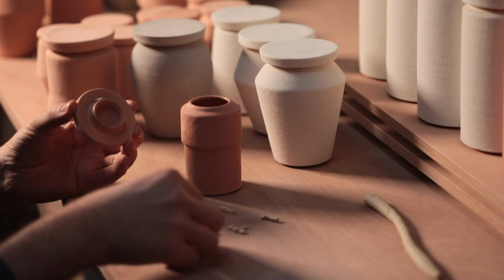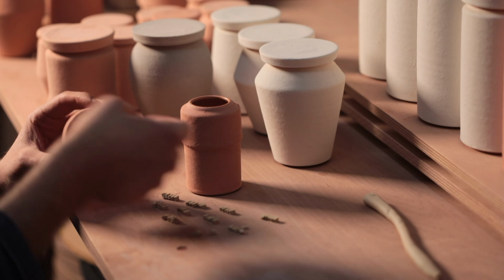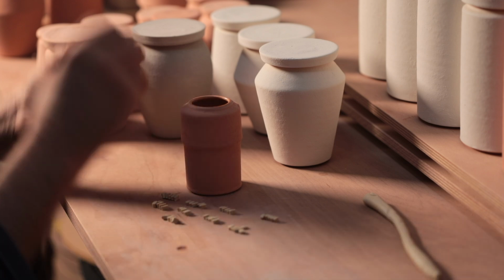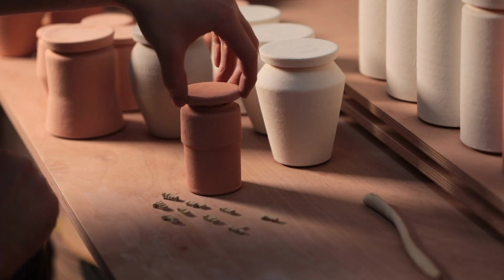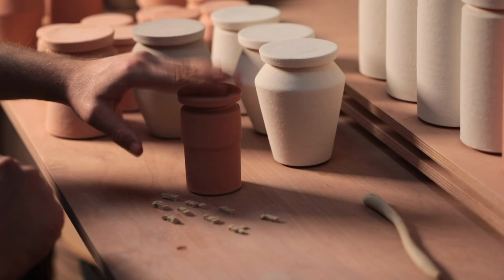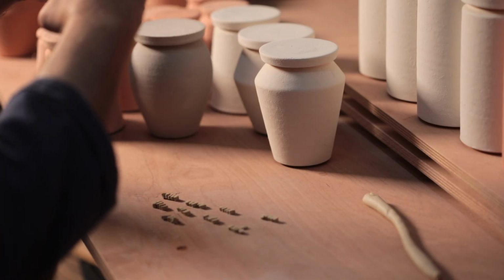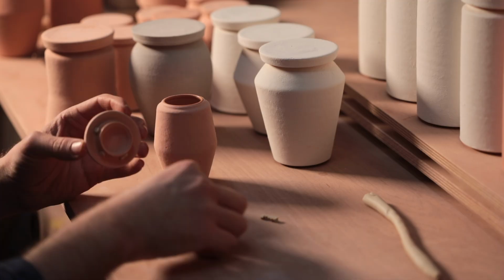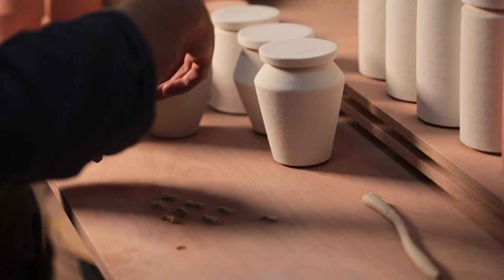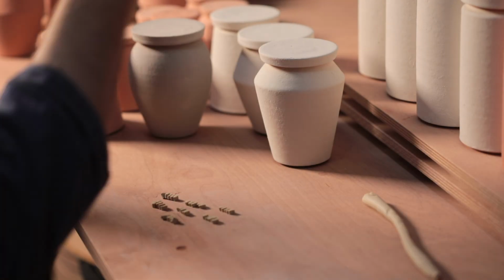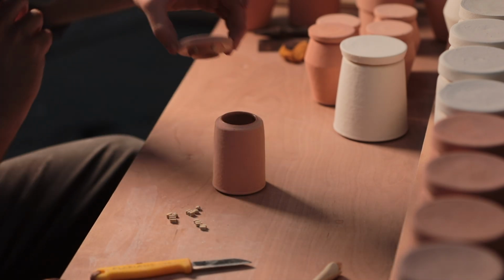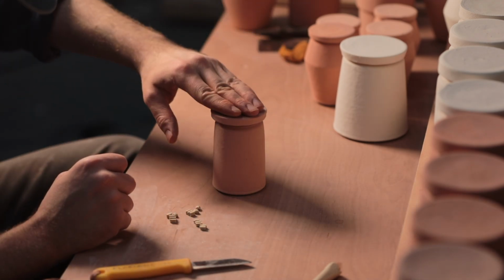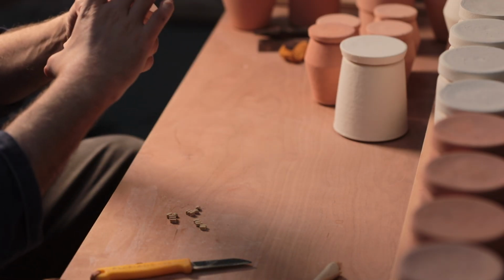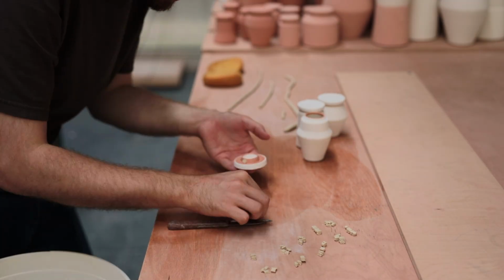I roll out long coils of the wadding and then cut them into much smaller bits, and then I press 5 of these beads of wadding onto the wax on the underside of the lid and then press it into place on the body of the jar, making sure that the clay of the lid doesn't come into contact with the rim of the jar, as at this higher temperature, if clay touches clay, there's a chance it can fuse due to all the soluble salts in the feldspar that volatilise during the firing, flashing and colouring the clay red.